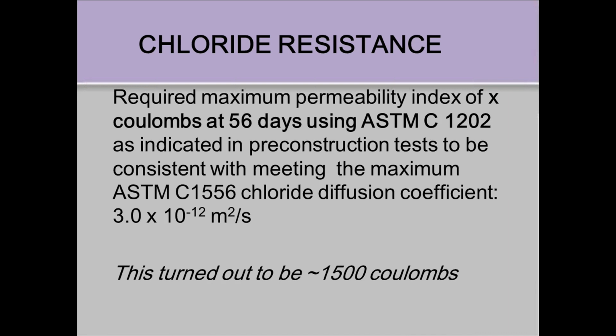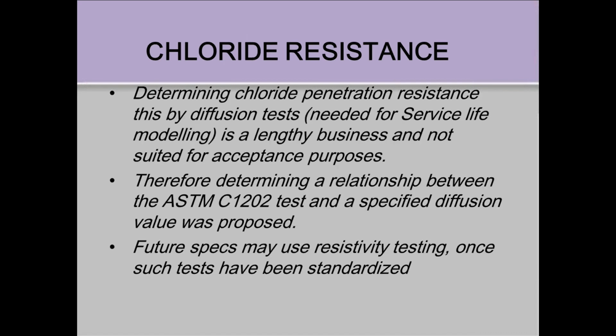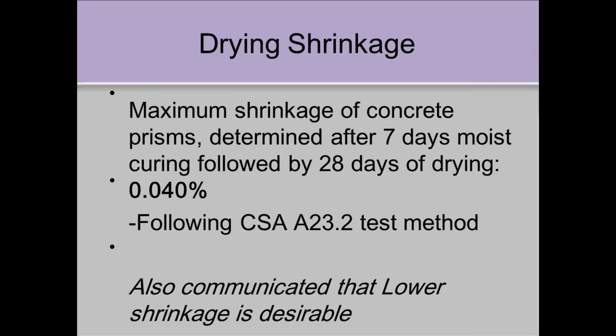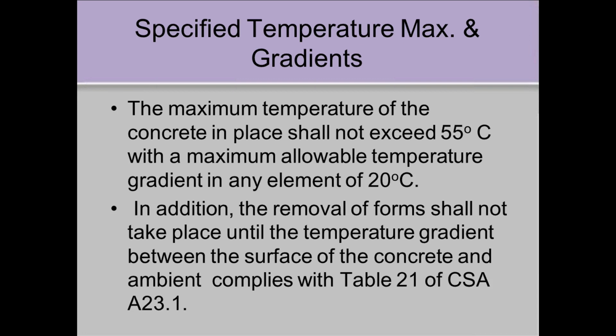So get a rapid test in there just as a surrogate for that during the construction acceptance process. We wrote that in. And the same with shrinkage. We set a shrinkage spec. There is an option in the Canadian standard. And we set gradients. We set 55 as our maximum temperature, with a maximum gradient of 20.